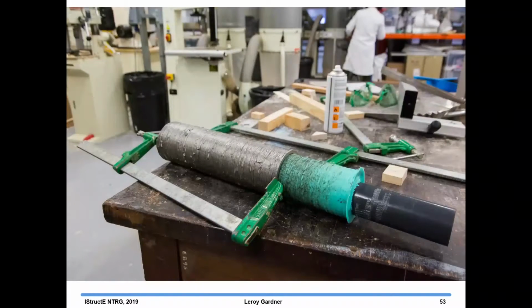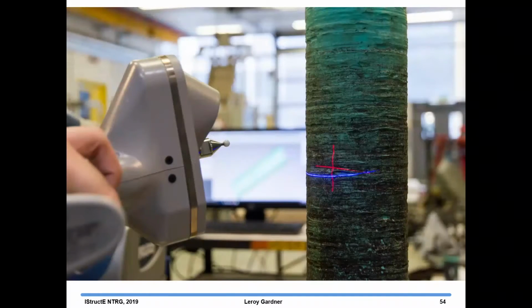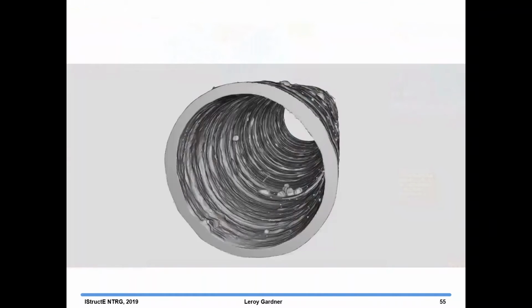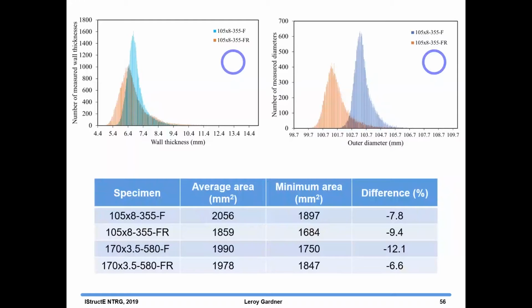It sounded really easy, but we had some real trouble getting some of these molds out. They all came out eventually, not all in one piece, but generally good. We then scanned the silicone casting, and then we merged the outer and inner scans to get a full 3D model of the specimens. And once you've got that, you can look at the geometry in quite close detail. So you can get information about the variation in wall thickness, diameter, and so on. And of course, 3D printed material is more variable in its geometry than conventionally produced material. This enabled us to capture how much that variation was.